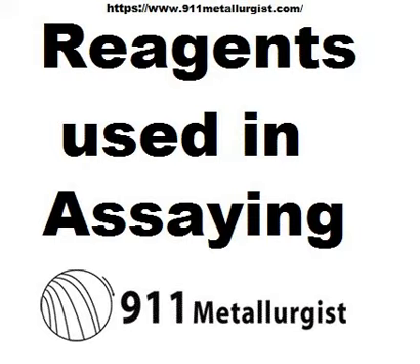3. Not precipitated in an acid or alkaline solution, but thrown down on neutralizing the latter: sulfides of vanadium and tungsten. Sulphuretted hydrogen is a strong reducing agent; ferric salts are thereby quickly reduced to ferrous. In hot solutions, nitric acid is decomposed. These changes are marked by a precipitation of sulfur, and the student must be careful to pass the gas sufficiently long, and not be too hasty in concluding that no sulfide will form because it does not at once make its appearance. The best indication that it has been passed long enough is the smell of the gas in the solution after shaking. Sulphurous acid, H2SO3 — the reagent used may be regarded as a saturated solution of sulfur dioxide in water. It may be purchased and keeps for a long time, and is used as a reducing agent and should not be diluted.